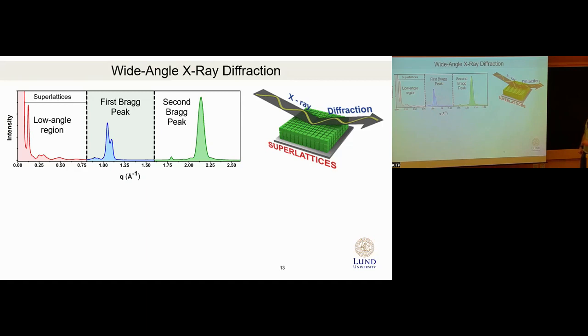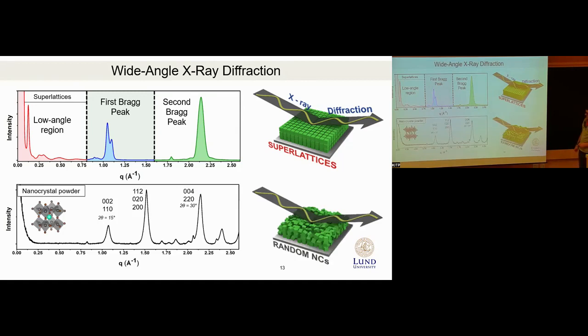So for the superlattice films, we saw some peaks in the low angle region, which one would expect because of the periodicity of cubes. And then we saw some unusual effects. For example, in the first Bragg peak, it had some fine structure. For reference, this is how a similar diffraction experiment looks for disordered, randomly ordered, essentially powders of nanocrystals. You have all the Bragg peaks which one expects from the orthorhombic perovskite, which are broadened because of finite nanocrystal size. And in the superlattice instead, first you have only a few Bragg reflections due to preferred orientation. And then, moreover, there is some intensity modulation, as we call it.